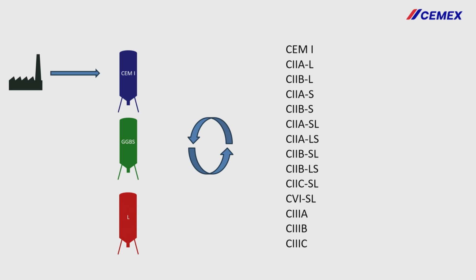And then there is a third option, which is taking a silo of limestone fines. Okay, so a BS 7979 limestone, sticking with CEM I if you choose to, because again, lots of work going on in the industry about reducing carbon in CEM I. Still having a silo of GGBS, and you may notice I've focused on GGBS rather than fly ash. The option with fly ash still exists, but most people are talking about CEM II/A-L plus GGBS because, let's be honest, it gives you a lower carbon concrete.